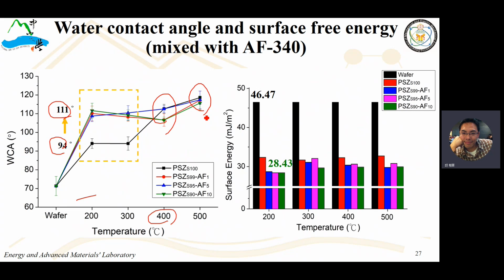The reason why is that the fluorinated resin, this fluoride complex, decomposes at a temperature higher than 300. So the fluorinated compound will decompose when the cross-link temperature is higher than 300. That means we cannot find any hydrophobic effect from those fluorinated compounds.